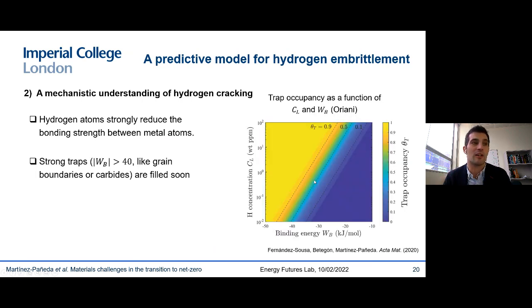And then the other side of the coin is people that are trying to argue that maybe we could use traps in our favor, and this is the idea of a beneficial trap. So you could use, for example, carbides. Let's say, assume that carbides are not involved in the fracture process. Then you could put a lot of carbides into the material, and if those carbides have a strong binding energy, then they're going to be full very soon. So the hydrogen is going to like to go there. The larger the binding energy, the more energetically favorable it is for the hydrogen to go there. So those strong traps may help in attracting the hydrogen so that the hydrogen doesn't go to fracture regions like grain boundaries, for example.